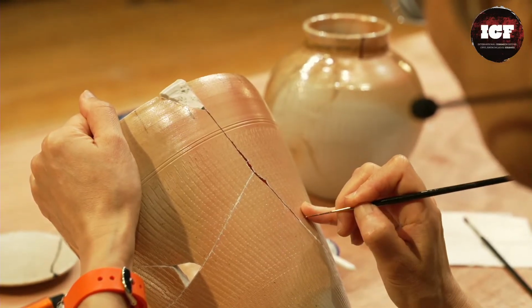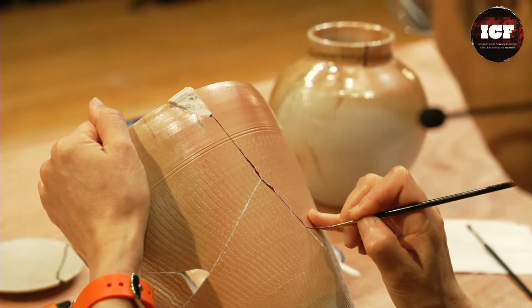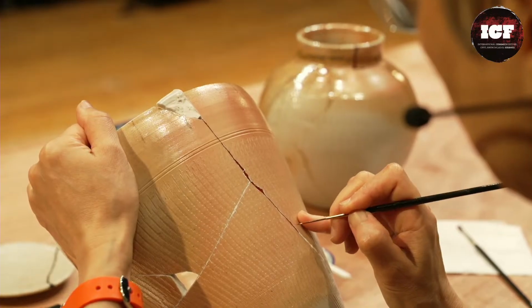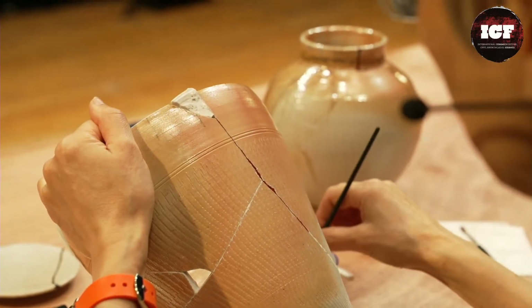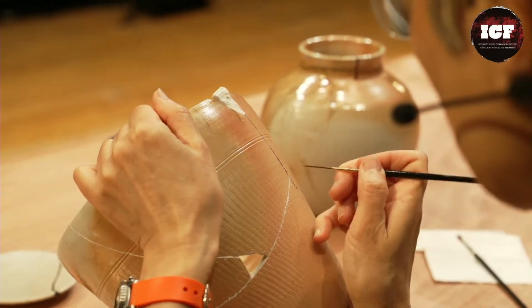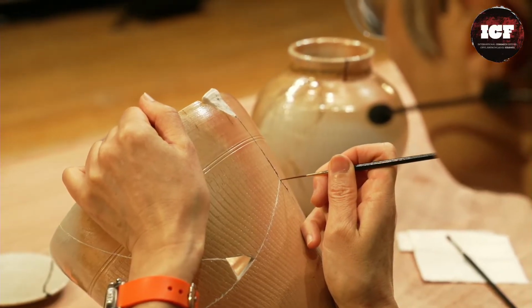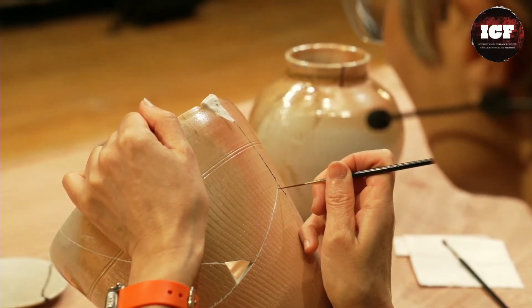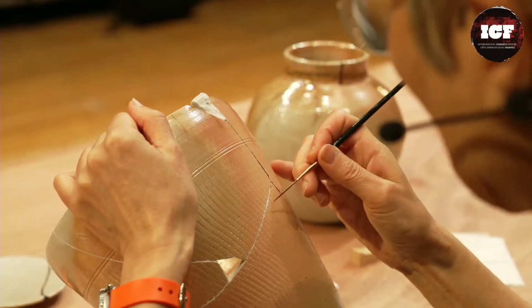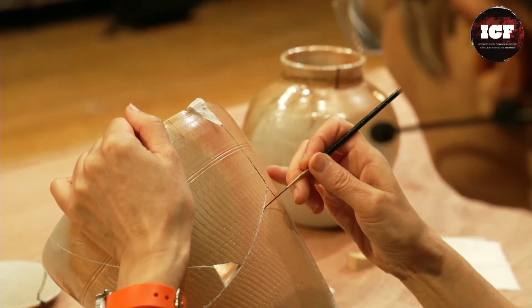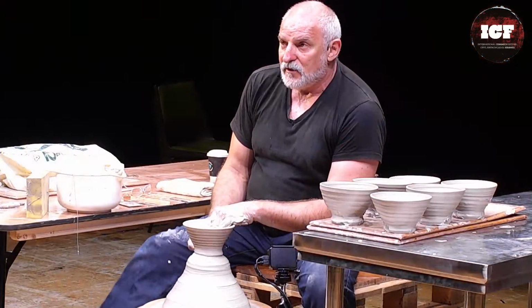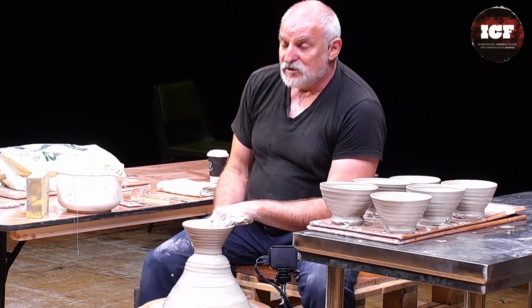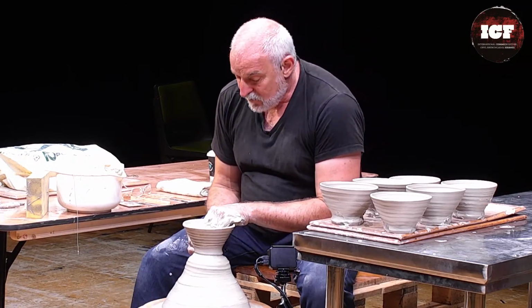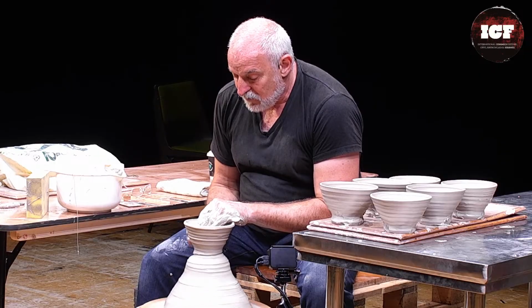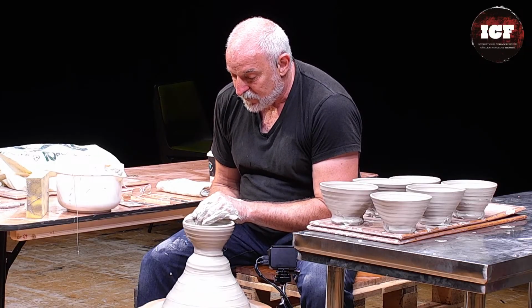So, to prevent the cristobalite from forming, if you crash cool, it doesn't have time to form. Crystals grow in a liquid matrix, so you need to crash cool. What I crashed it was from 1300 to 1100 in 30 minutes. So there's no time for the crystals to form. Therefore, there's no stress in the silica. Therefore, you don't get dunting.